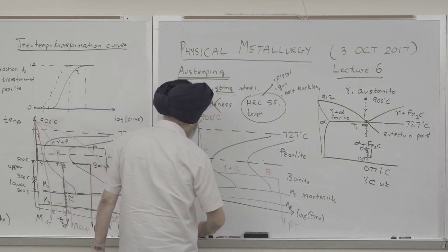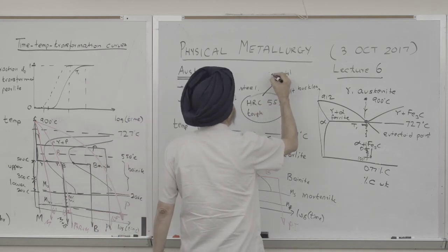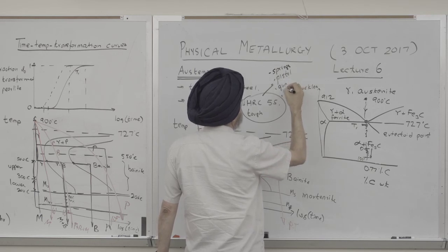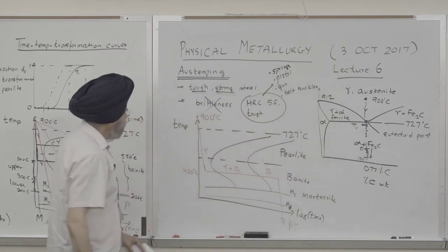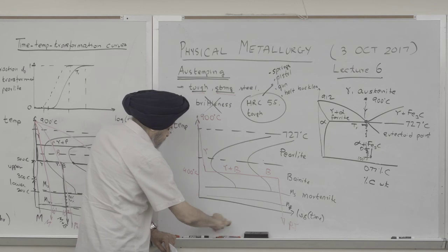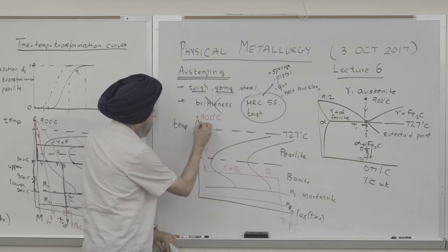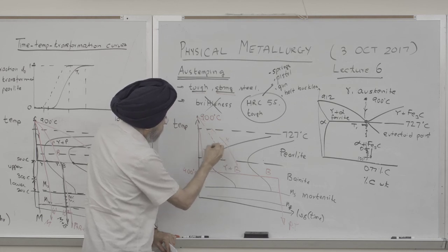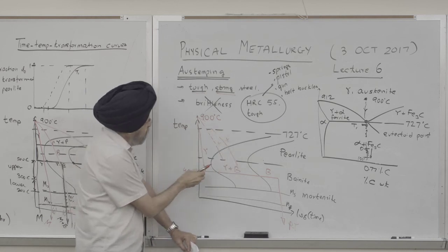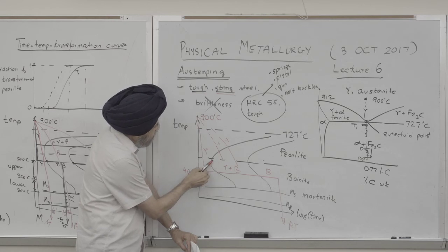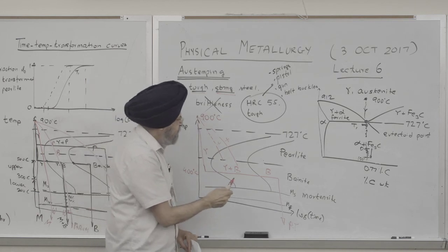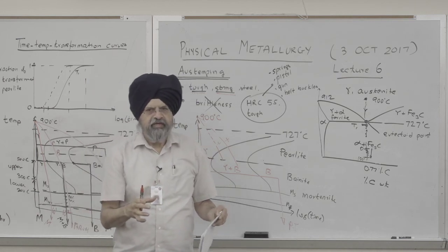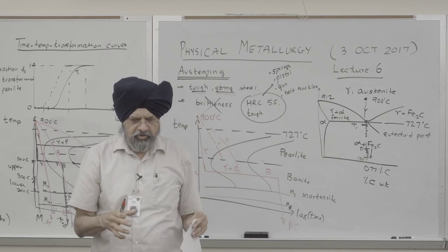So you can also make springs, pistol parts, gun parts, belt buckles. But notice that if you're cooling slowly or slower, you end up over here or you end up over there. So this is no good. So to cool the steel fast, you want to make sure that it's not too thick. It's got to be thin, because if this piece of steel is too big, it takes longer to cool it.